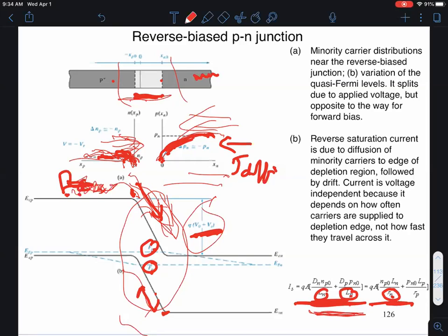Now, once again, if you look at these terms, let's see what are the important parameters, okay? So you see that if I wanted a low leakage junction, and of course, that's what you want in a typical device, what you want to do is have a long diffusion length, Ln and Lp, or equivalently long minority carrier lifetimes, tau n and tau p. The way you achieve long minority carrier lifetimes or long diffusion lengths is have a device with very, very few defects, okay?